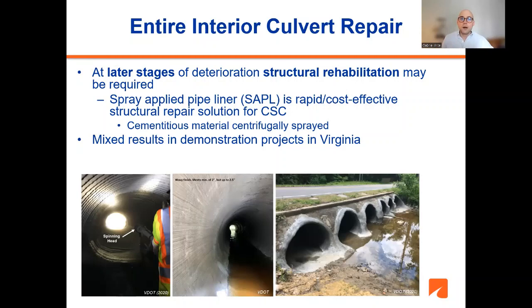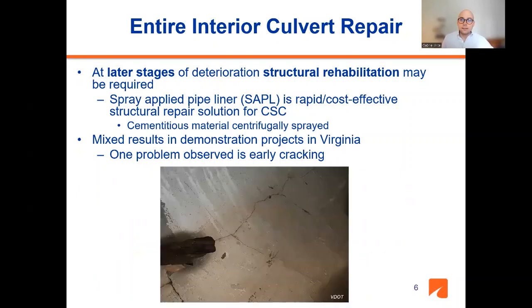So now, what is the problem with this technique? As you can see, it has been done. We have had some demonstration projects in Virginia. But the problem is that in some of these repairs, we have observed some early cracking. And this is an image right here of how this cracking looks, and why this could be a problem when you do the entire culvert repair.